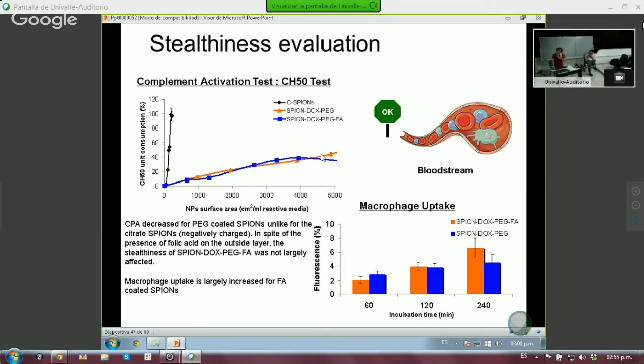Anyway, we have the same activation test. But now when we look at the macrophage uptake, I'd like you to just look at the red and blue as a function of time. As you can see, for an incubation time of 60 minutes, when we have the folic acid, it's little. Then if we go to 120 minutes, we have the same fluorescence, the same macrophage uptake, and you can see here they are both equal.